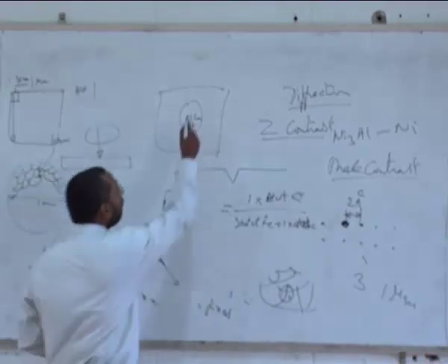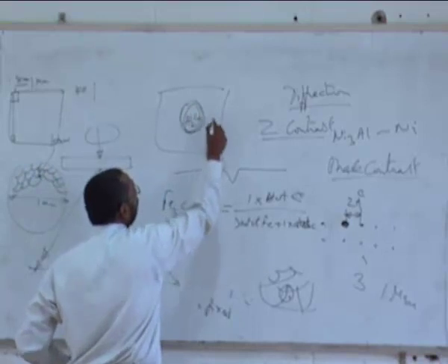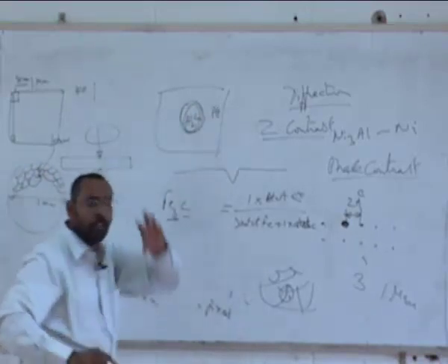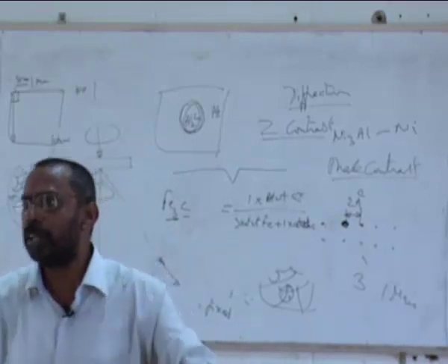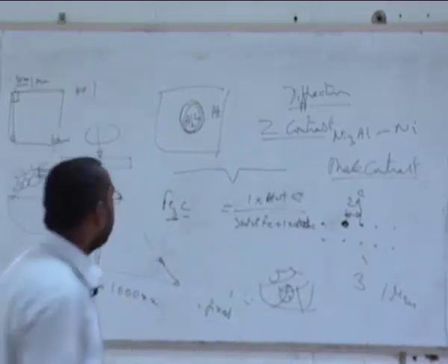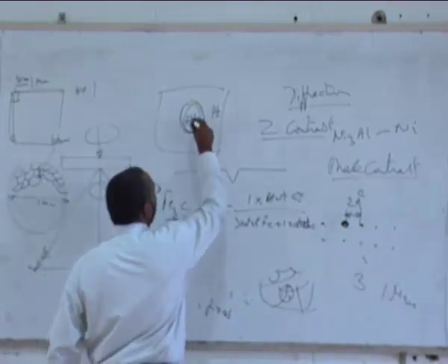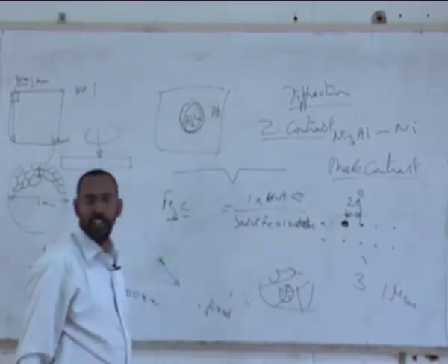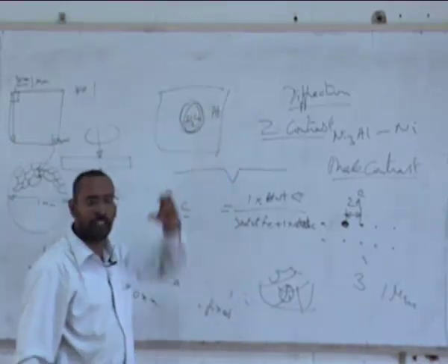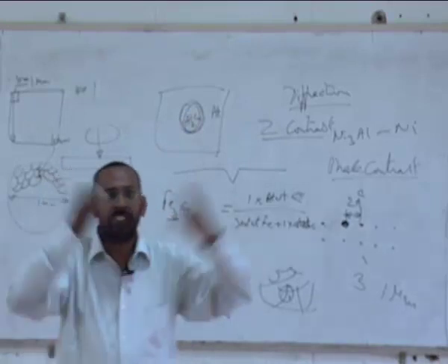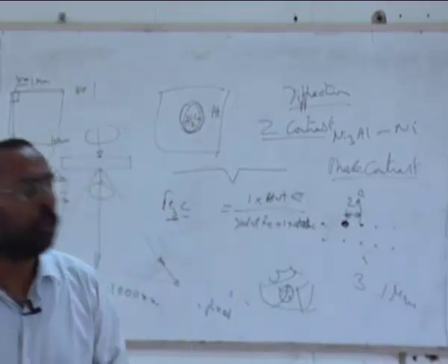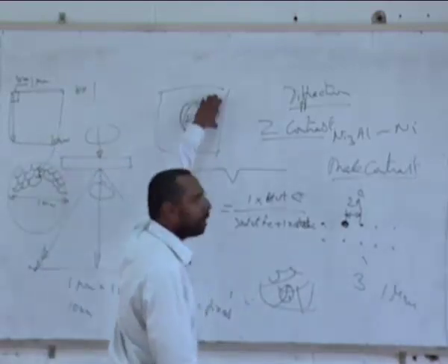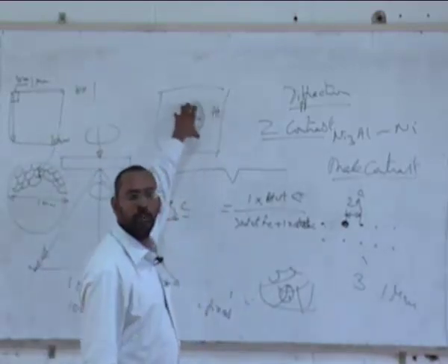So that means this particular region has more electrons per unit volume than this particular region, because aluminum has a lower atomic number. So as a result, when the beam falls on this and on this, the number of electrons present per unit volume to scatter away the electron beam is going to be smaller in the aluminum region when compared to Al2Cu.